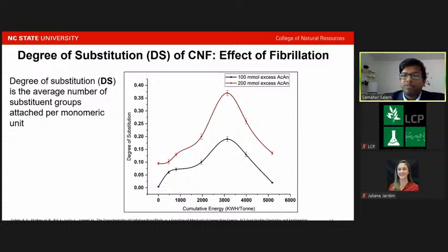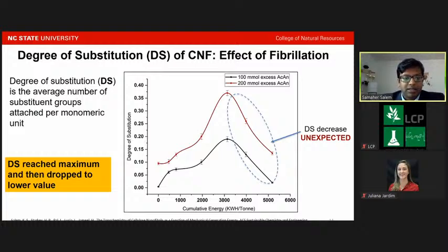However, after reaching this certain energy, the degree of substitution, that is the reactivity, decreased, even though the energy supplied was increased and the fibrillation increased. So this decrease in the degree of substitution was unexpected. This was not the hypothesis. This does not align with our initial hypothesis.